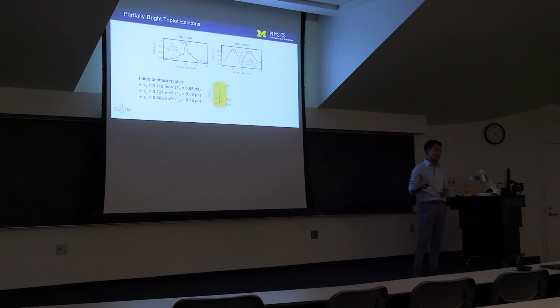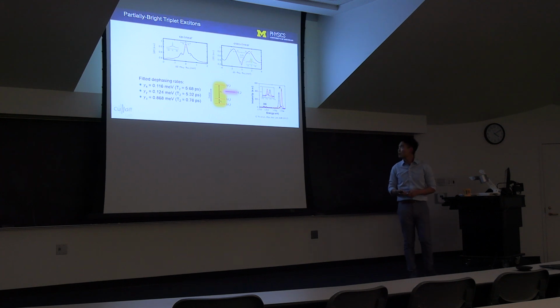So our hypothesis is that in cesium lead iodide perovskite nanocrystals, the dark state actually lies between states y and z. This model is perfectly corroborated by single nanocrystal fluorescence of nearly identical iodide nanocrystals, where they observe polarized doublets separated by omega 2 corresponding to emission out of x and y, but never a third peak separated by omega 1, which would correspond to emission out of state z.